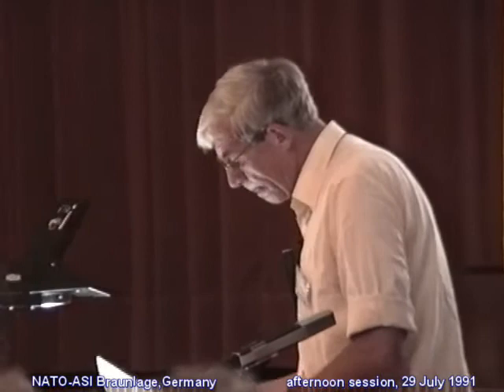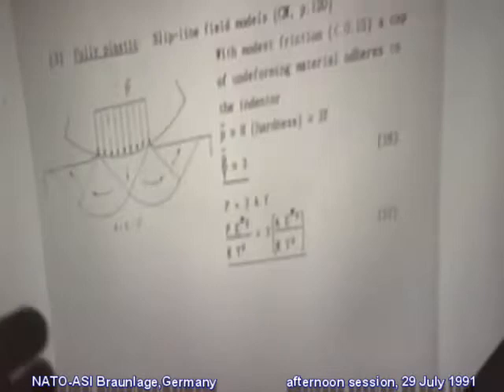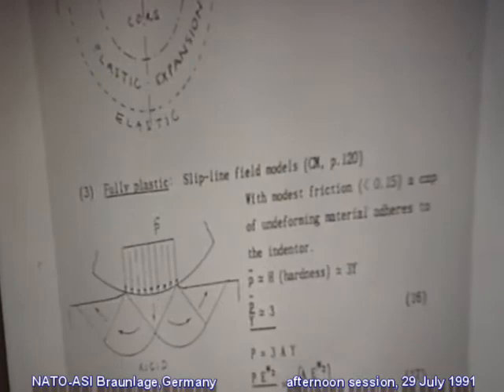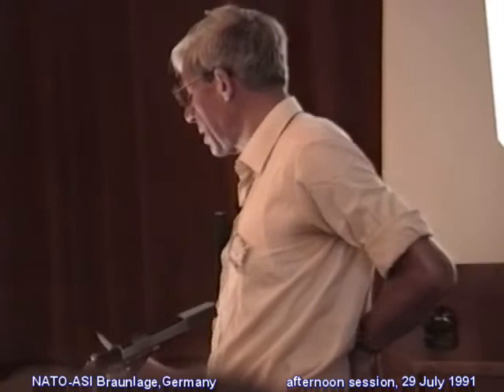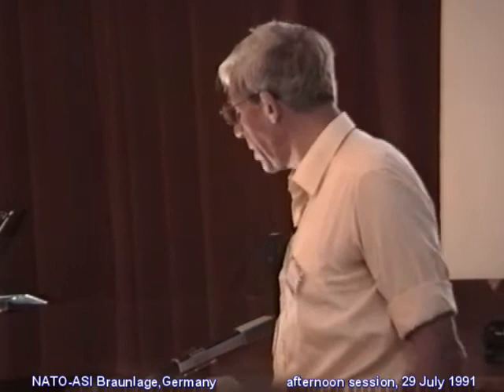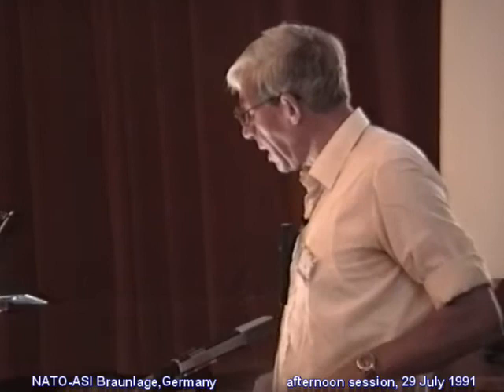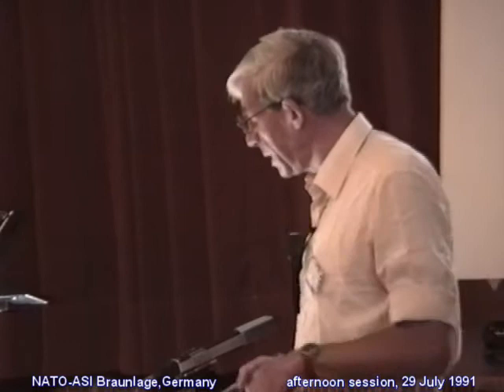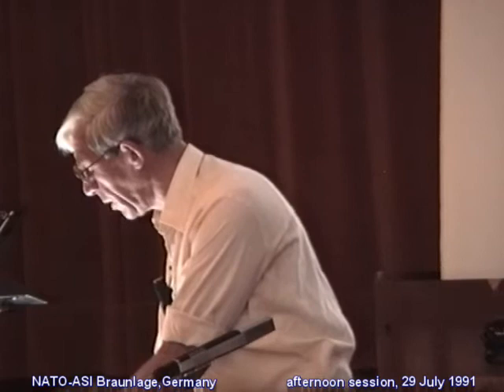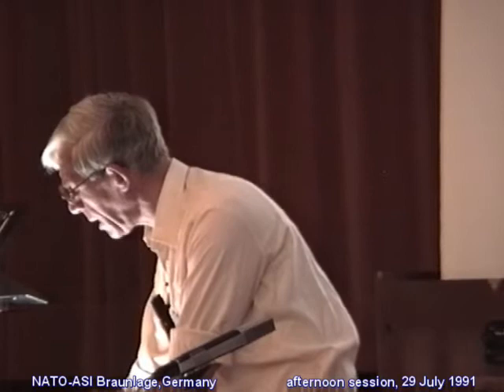Now the second regime is when the plastic deformation is contained within the solid. This is more difficult to analyze, although quite a lot of solutions are now coming out, numerical solutions using finite elements, for that regime of loading, where we've exceeded yield below the surface, but it's not yet broken out to the surface. Some of you will be familiar with a rather rough and ready model that was suggested by Rodney Hill and developed by me some years ago, which gives this expression for the normalized mean pressure, again, in terms of this non-dimensional group, A, E star over R times Y.